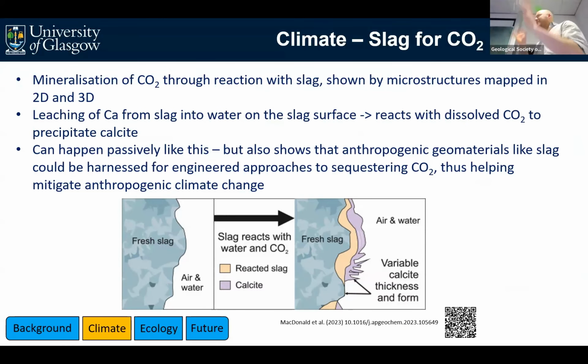So I guess we would try and summarize some of that data in a cartoon schematic model of what's going on. In this diagram at the bottom here, we've got some fresh slag, but that then comes into contact with water and air, and you have this reaction going on where you end up with a buffer zone of what I've called reacted slag, where the calcium has leached out, and that's then gone into precipitating, forming the mineral calcite. That's taken in CO2 from the adjacent air.